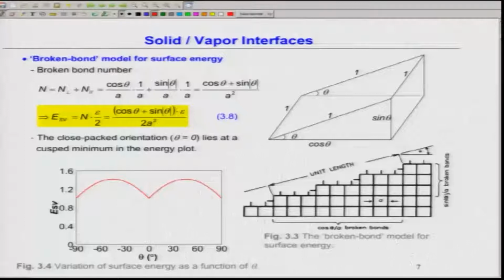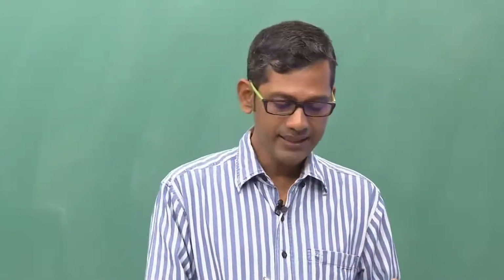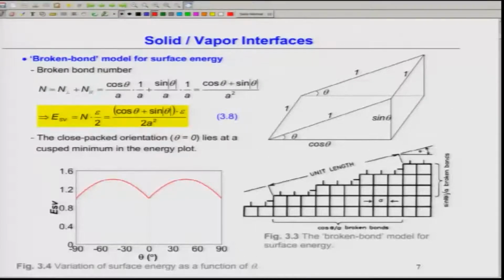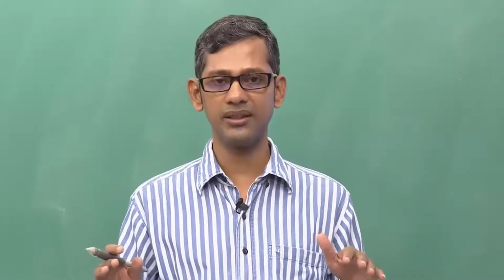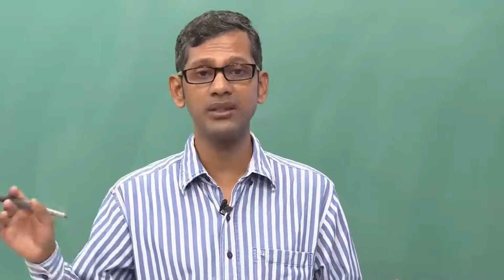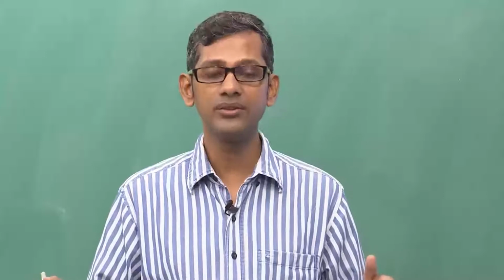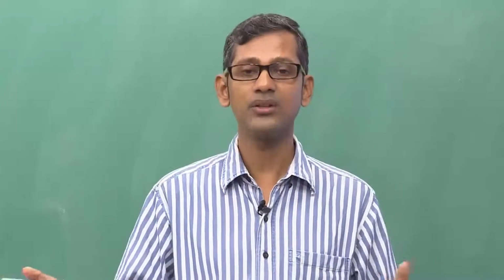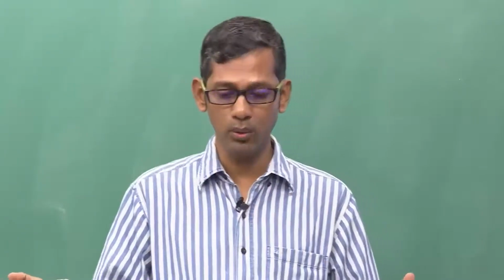Therefore these curves have minimum points, and these points are very important, because these are the points at which the surface energy will be lowest. If the system wants to decrease its total energy, which is equal to G0 plus A gamma, the planes which will be bounding surfaces must be the ones which have the lowest energies, because if gamma is low then A gamma will be low.